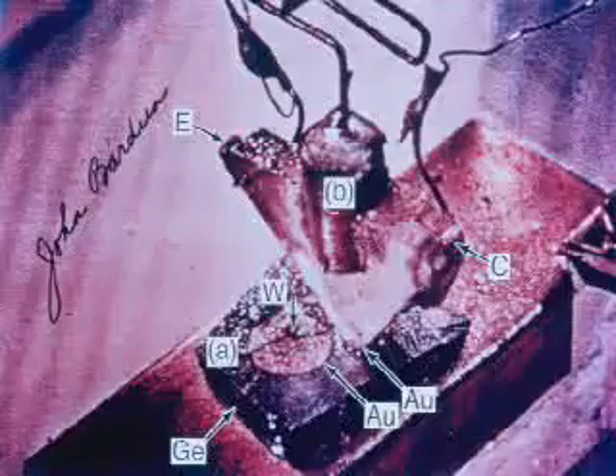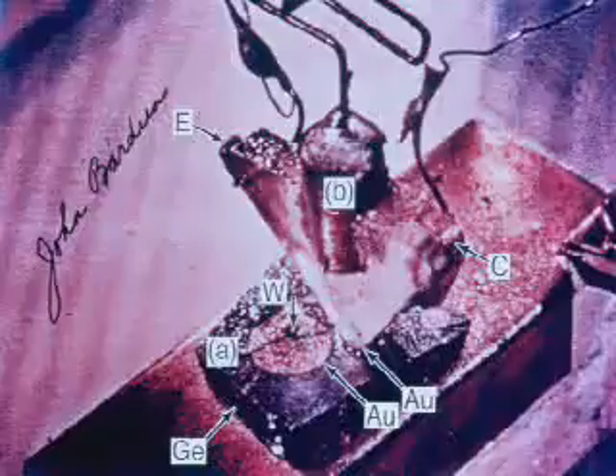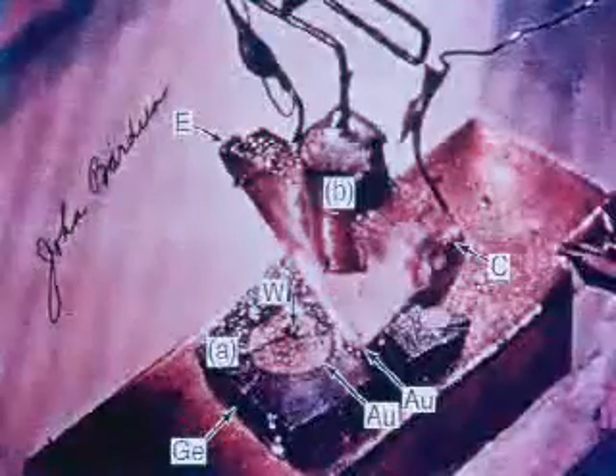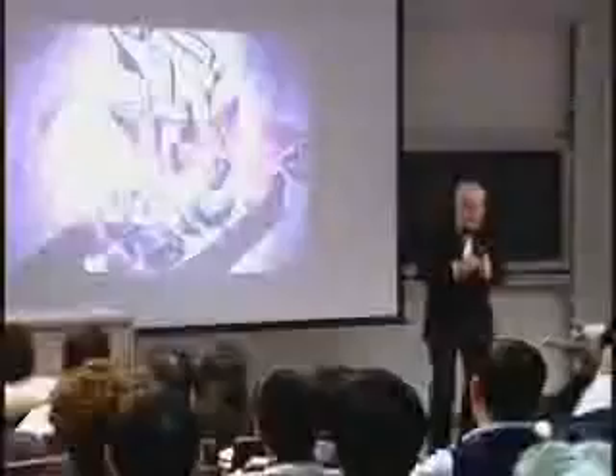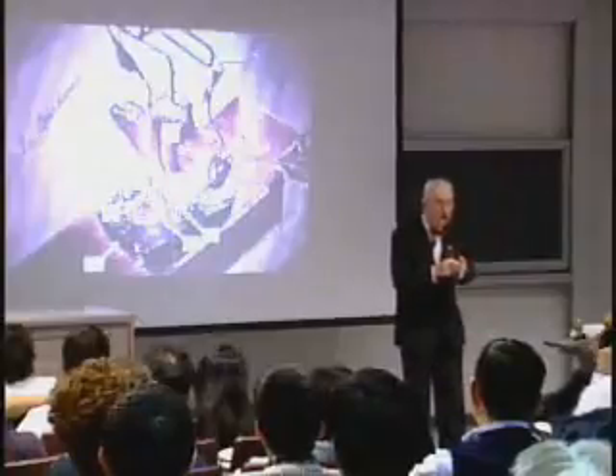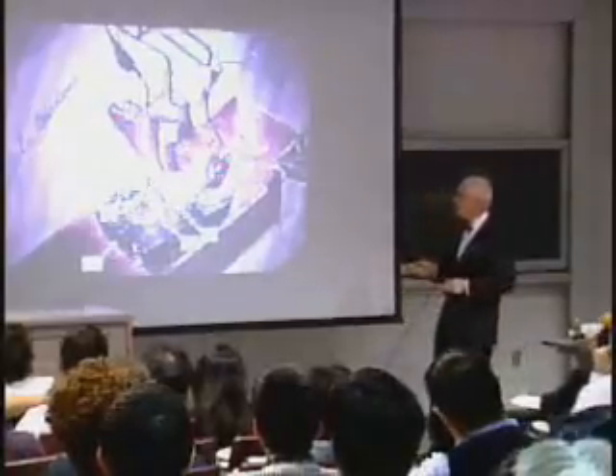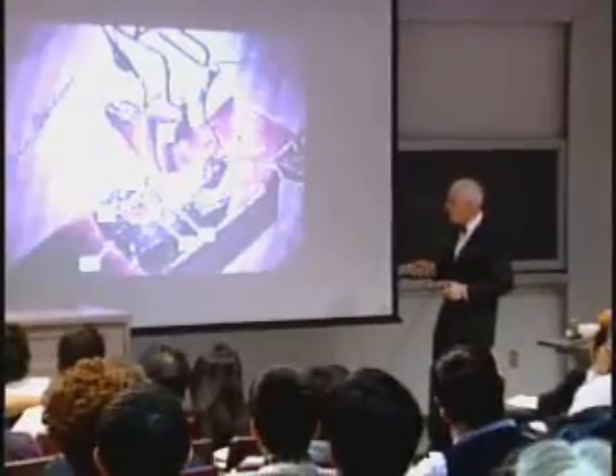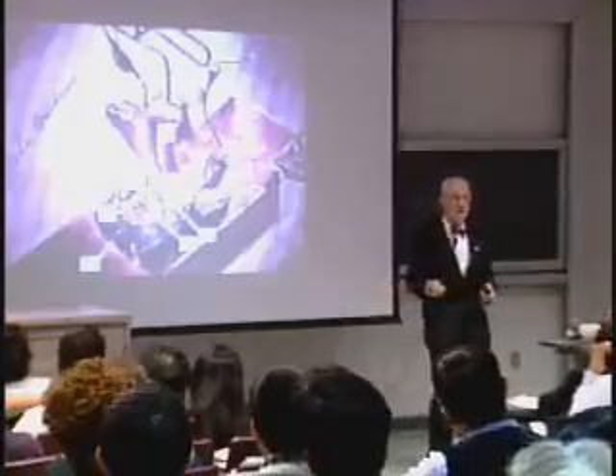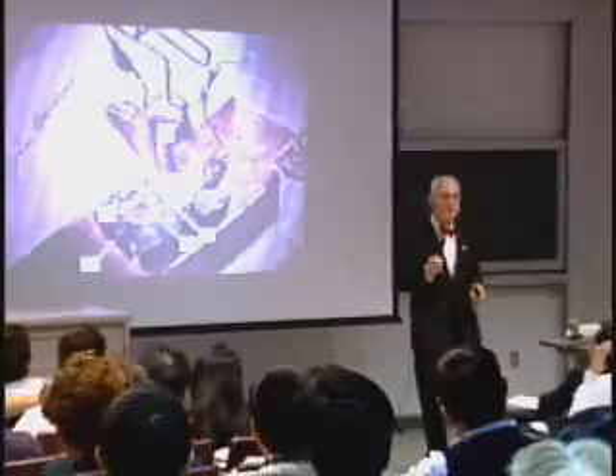Now you can see I modified Bardeen's picture. This one that he signed. You see, here's experiment A, the gold disc with the hole in it, and I indicated where the tungsten point should have been, but then Walter moved it out here, and with different bias than field effect bias, something different, he got what looked like transistor action, and so then they made experiment B. This was experiment A. Experiment B is to take this plastic wedge, wrap a gold strap around here, split the strap on the bottom, then you got two electrodes. You got one that we now call an emitter and the other one that you call the collector, and so I labeled emitter up here and collector up here. It could have been the other way around, and I indicated where the gold strap went around here. And here then is transistor number 1, 16 December 1947.